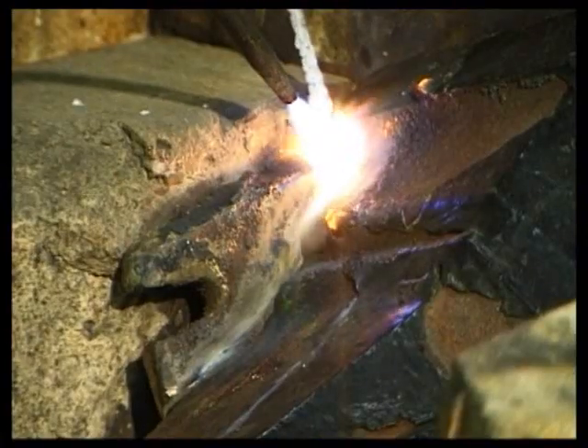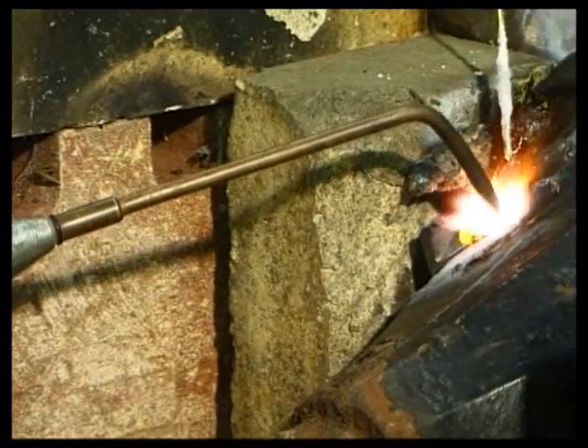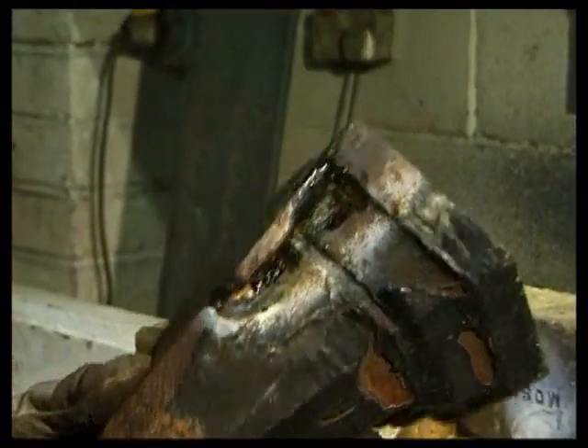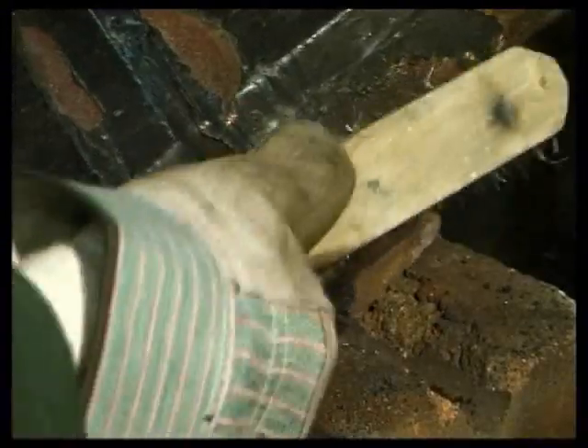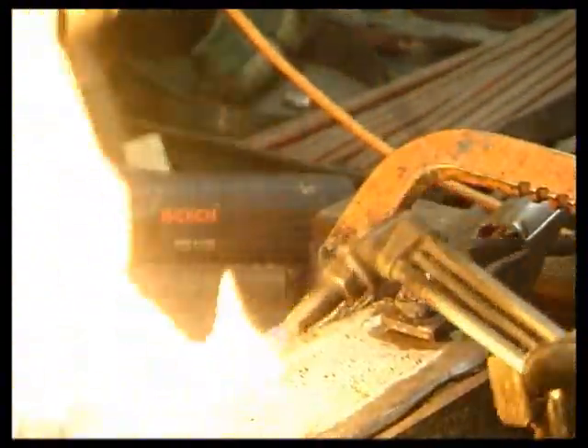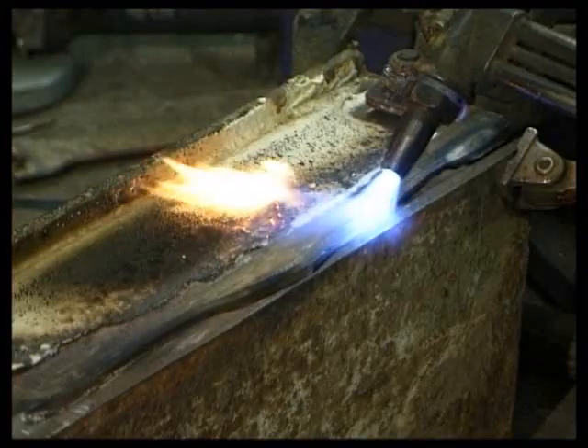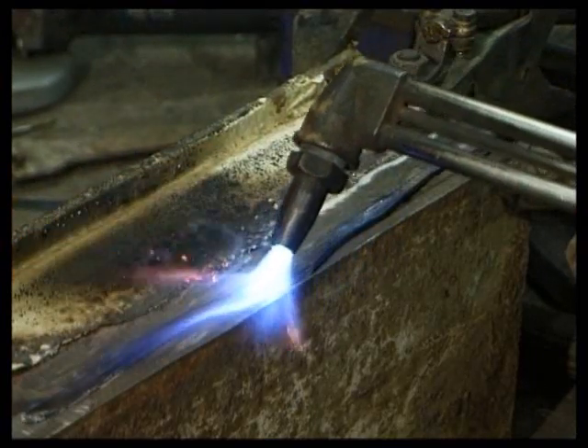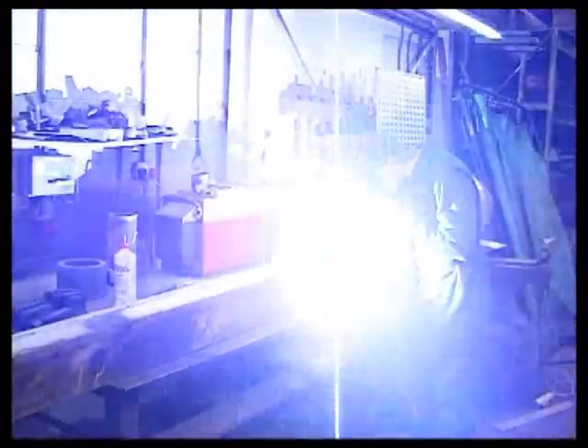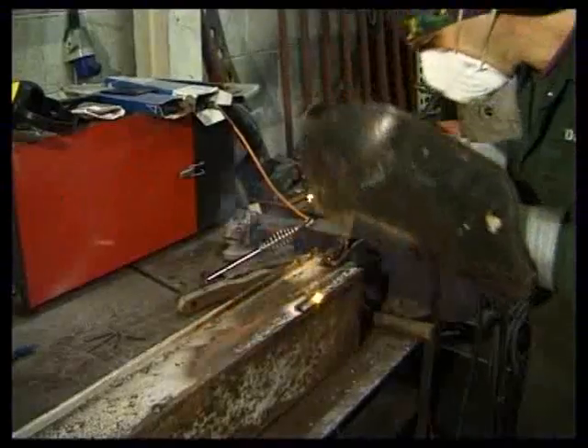For cast iron, gas welding is better than arc welding, particularly on thin sections. The flame temperature is much lower than that of an electric arc and the metal is heated more slowly. Casting should be heated slowly before arc welding, then cooled slowly afterwards if cracking is to be avoided. Small parts can be heated with a gas torch, but a special furnace may be needed to control the heating and cooling of large castings. On the whole, therefore, it's better to repair castings by bolts, plates or stitches wherever possible, rather than subject them to the stress of heating.